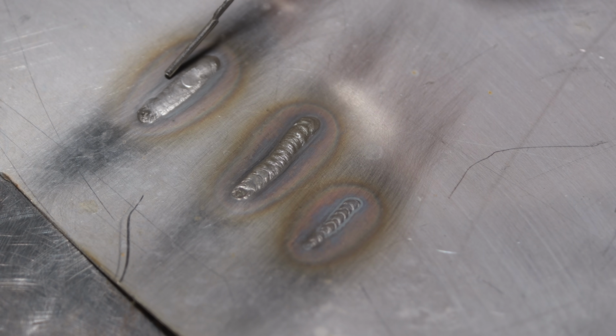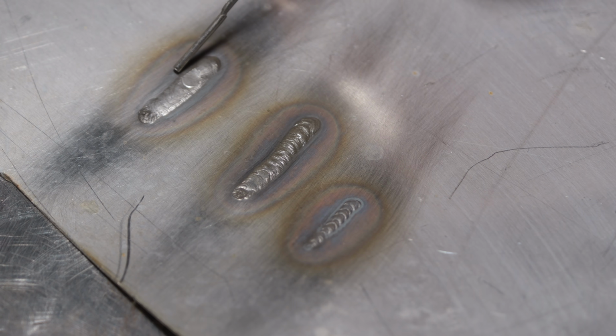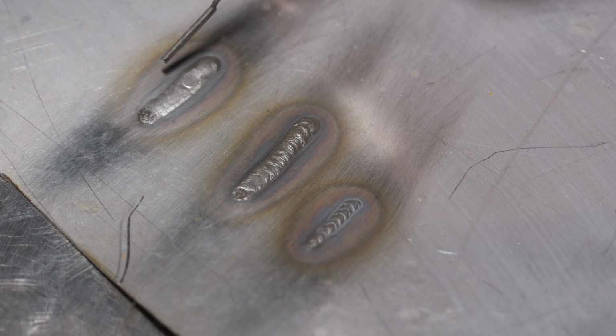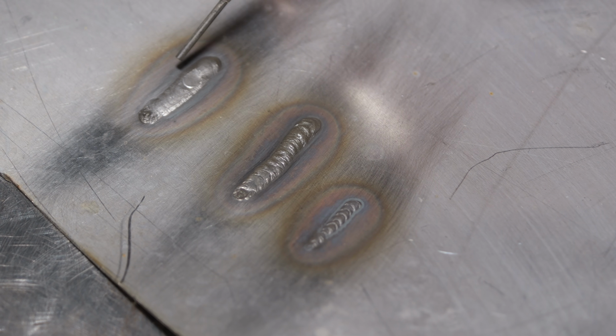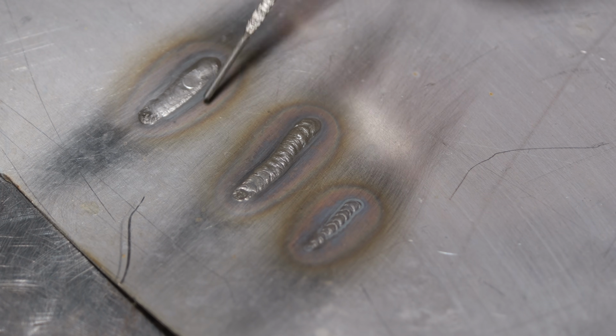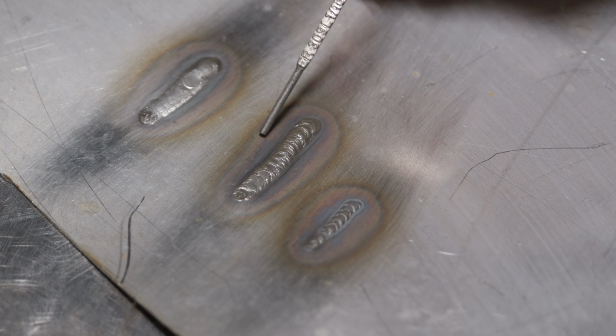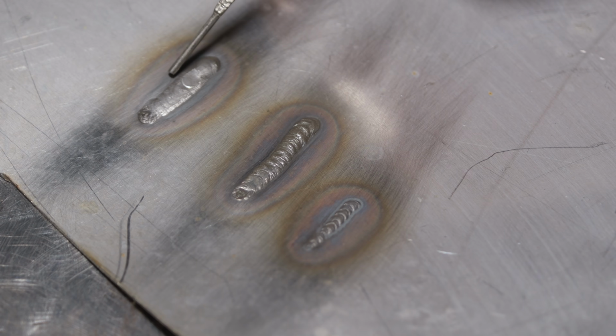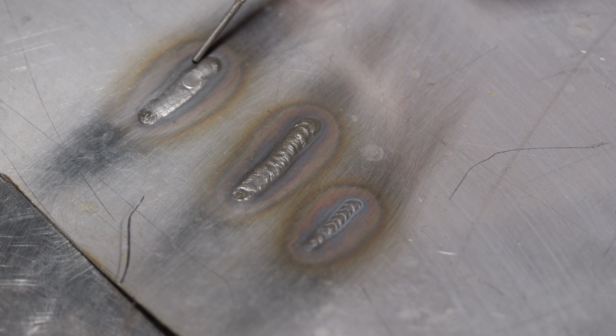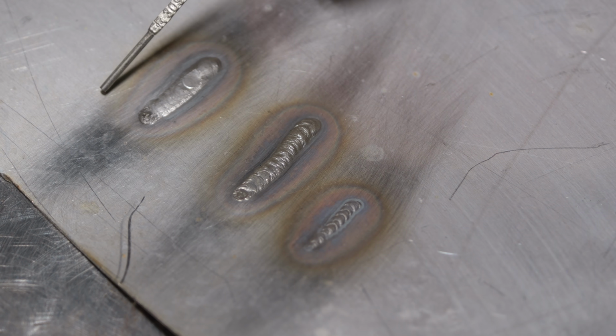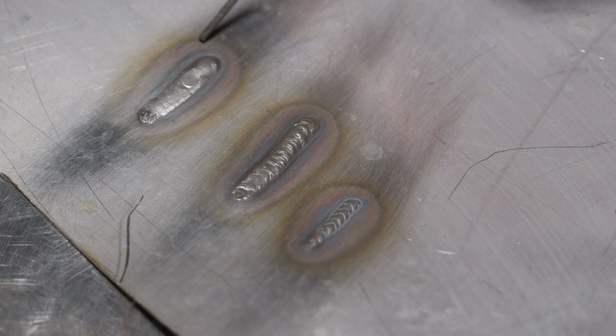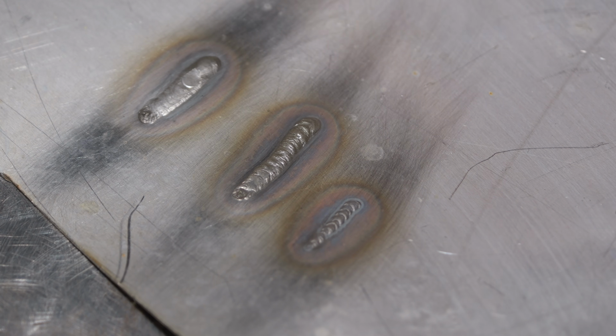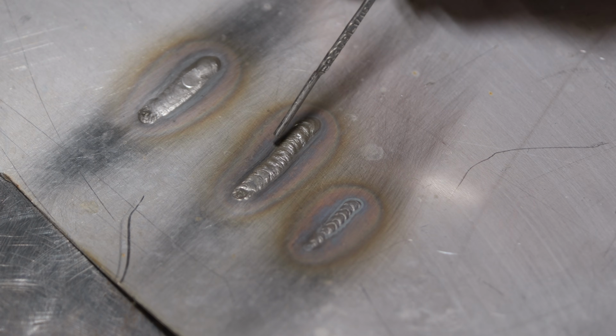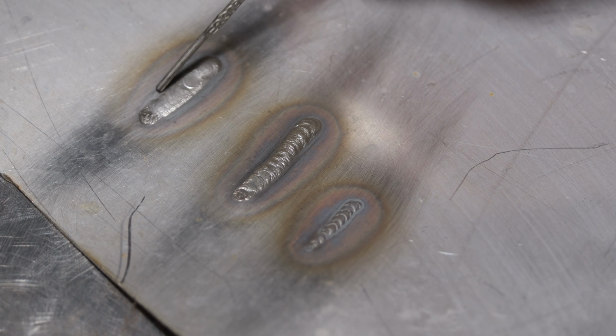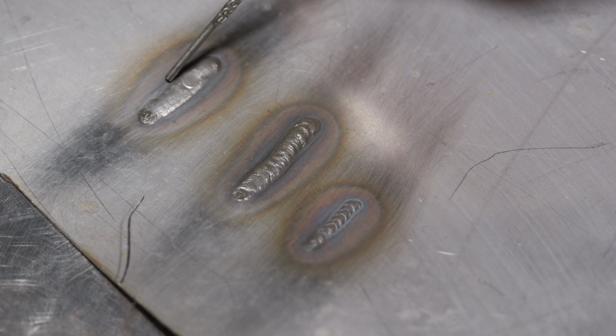Now, it's very common with ornamental stainless work like hand railings and such that I've seen, where because they're not purging the area good enough around where they're welding on the surface, if you get any of this on the surface and it doesn't clean off with a brush, it will rust there. Now, this is probably not much deeper than surface level, so if you took a flap disc and cleaned all this off to bright and shiny, it won't rust any more than a base material. But in the state that this is in right now, this will get rusting and pitting.